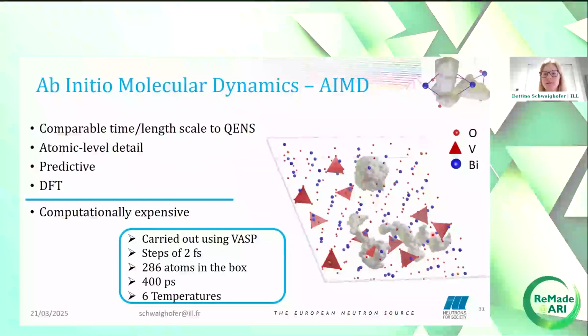As I mentioned in the introduction, molecular dynamics in general, and ab initio MD as well, gives access to a comparable time and length scale as quasielastic neutron scattering. The advantage of ab initio molecular dynamics is that it provides atomic level detail and is predictive, so you do not need to make assumptions on the diffusion pathway. But it is based on density functional theory, DFT, which means that it's very computationally expensive, and it's not feasible to reach nanoseconds of simulation time or simulate very big structures.